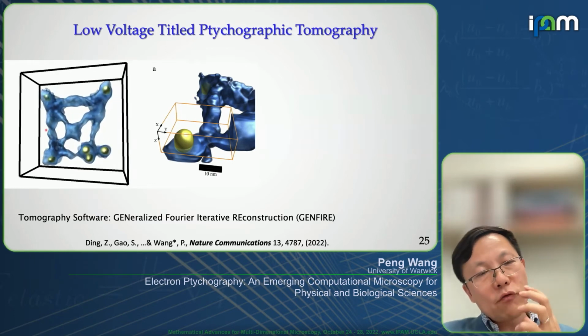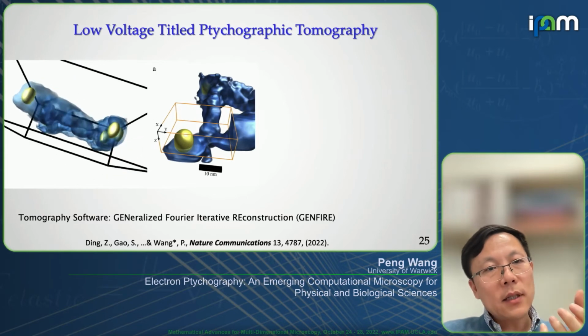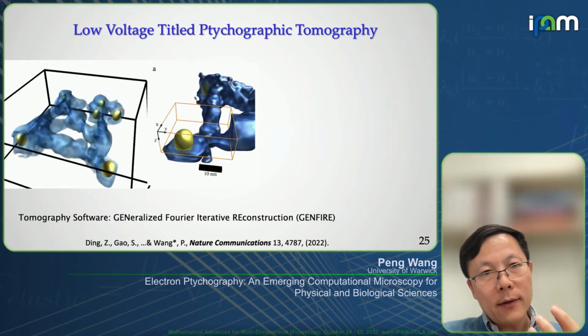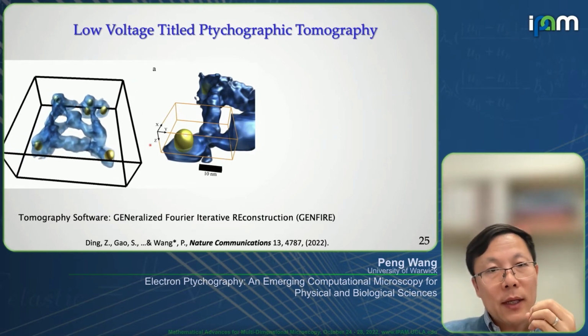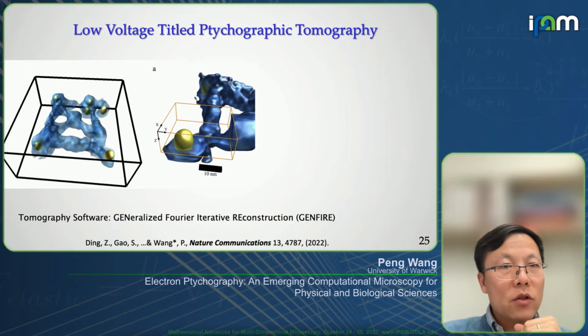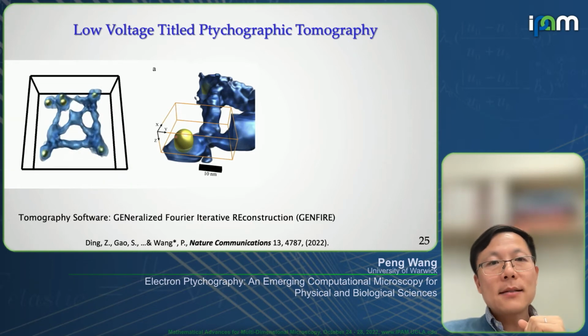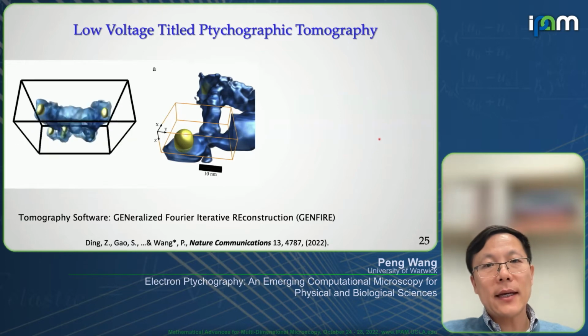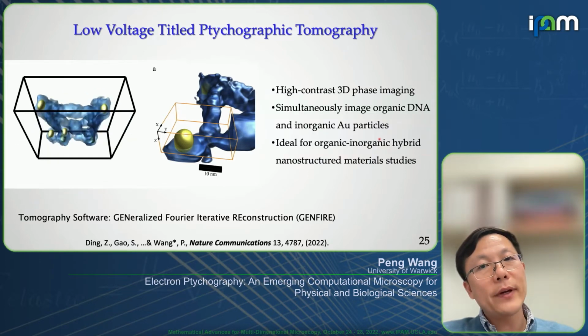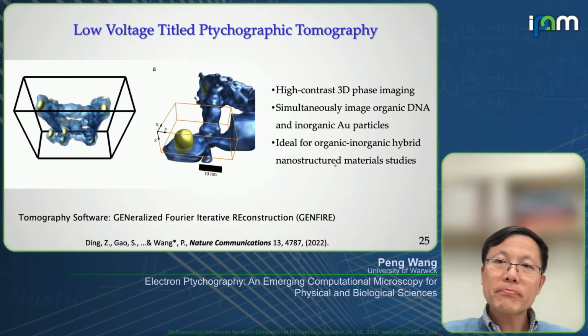at the corner. I think it's really good to see that we reconstruct the gold particle together with this DNA component, and especially, I have to point out that we're able to see the contrast of the DNA component around the heavy-atom gold particles. So this ptychography method really gave us a high-contrast 3D imaging capability, which can simultaneously image both the organic part and the inorganic part of some of these hybrid nanostructure materials.